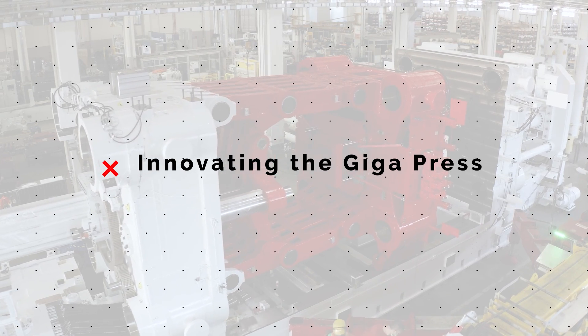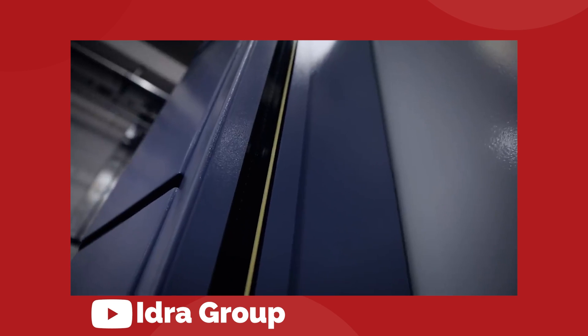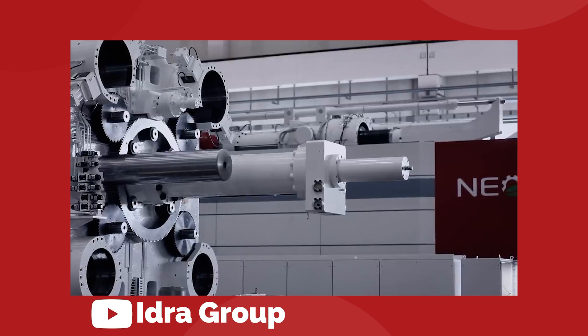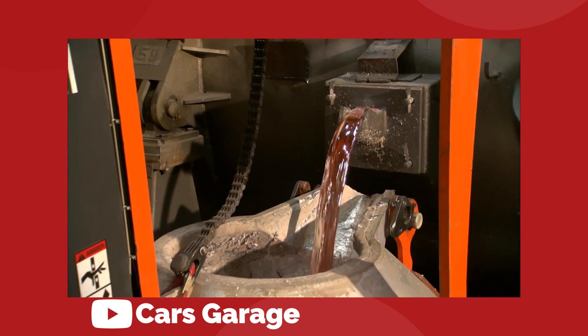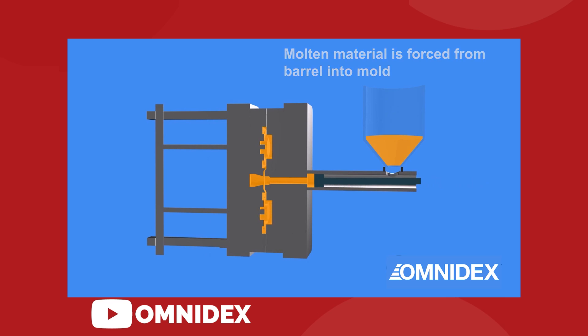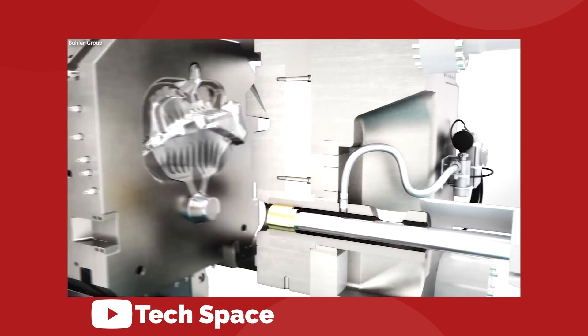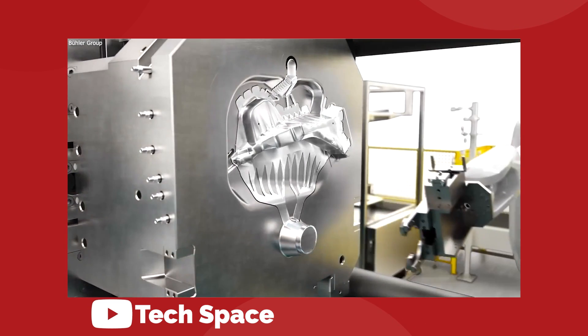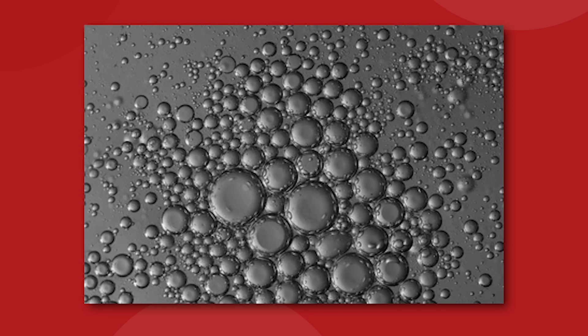The reason it's so hard to scale up a technique like casting is because it's a very finely balanced thermodynamic process done under very high levels of pressure. Molten aluminum is pressed into a die mold at high speed, and that liquid metal has to fill the mold perfectly and evenly before cooling into a singular strong component. The larger and more complex the mold, the further the metal has to travel, and the greater the chance that something will go wrong. If they press too fast, there will be bubbles in the metal and the structure will be ruined. If they press too slowly, the metal will cool before the die is filled, and the part will be incomplete and uneven.